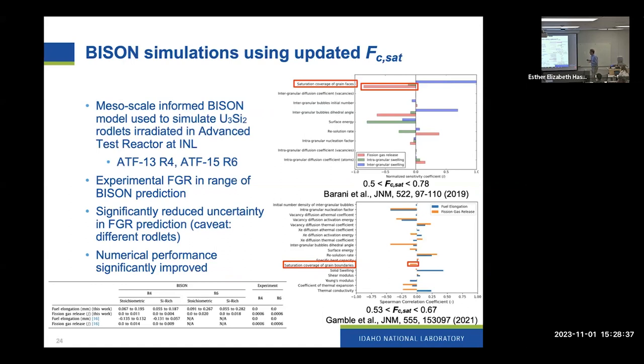We're able to pass this data to our colleagues that run Bison, and they ran some simulations using Bison of the irradiation of some U3Si2 rodlets in the Advanced Test Reactor at INL. The experiment numbers are shown here. And we saw that the experimental fission gas release was within the range of Bison predictions given these uncertainties.